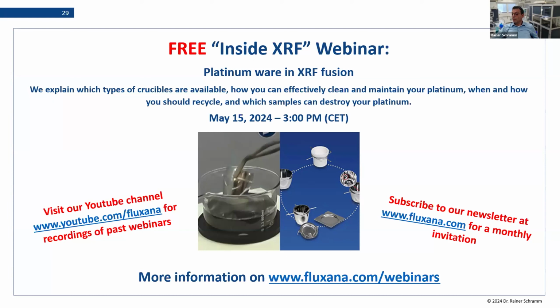Then it will work. Another question for gypsum: why not work with 8-gram borate, coarse crystallize? Yeah, that's a good question, why it crystallizes for you. I know that for gypsum we also use iodides as additive, and 1-gram sample and 8-gram flux, and this should work then. So then it shouldn't crystallize. You should use the 6634 flux, and then this should work. So I don't see why not.